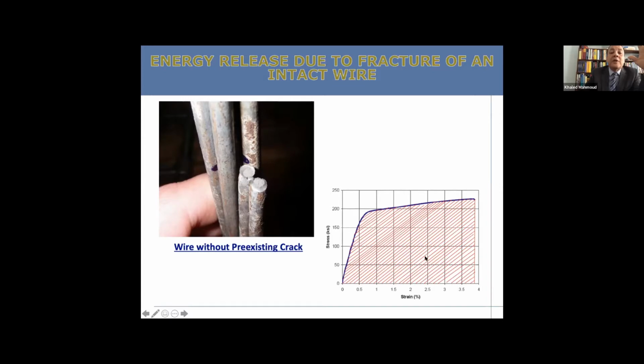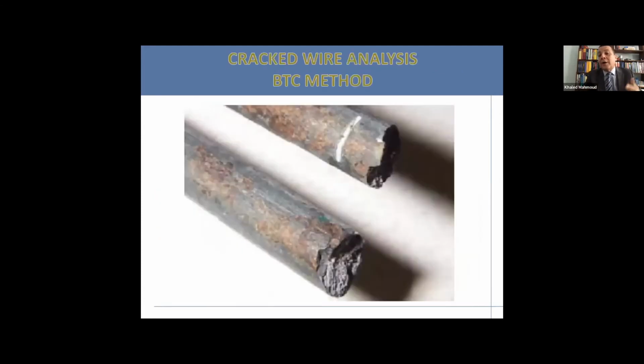And you see a tremendous area under the stress strain curve that actually represents the energy that it takes to break the wire. This wire doesn't have any crack in the fracture. This wire looks very good, without any section loss. It has the full 5 millimeter diameter. But just to save time and not to go back and forth, I'd like to bring your attention to the crack lurking right there. This is a crack in the wire, and that's where the wire break has taken place.